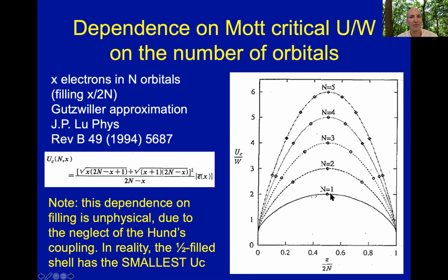So this is actually completely wrong physically. We know that half-filled shells are easier to make insulating. They require much lower U. And the reason for this is because of the Hund's coupling. This calculation here, I quoted the reference, but this calculation ignores the Hund's coupling. And as you will see later in the lectures, if you include the Hund's coupling, these plots do not look like this, but they look exactly the opposite like that. And this is all due to the Hund's coupling.